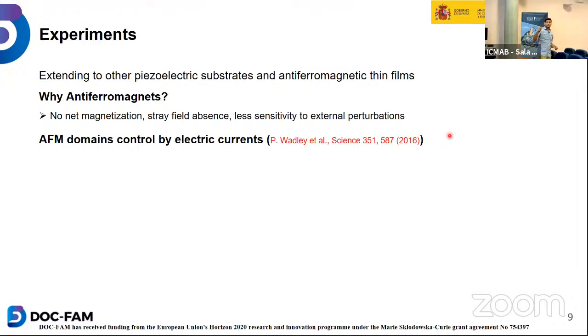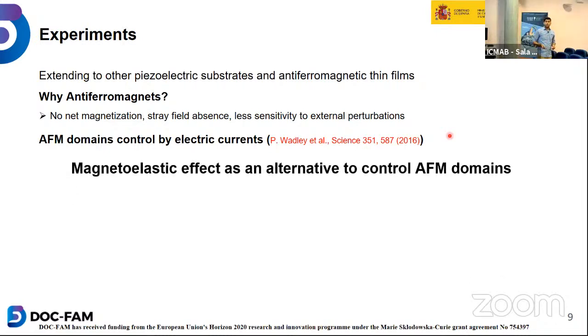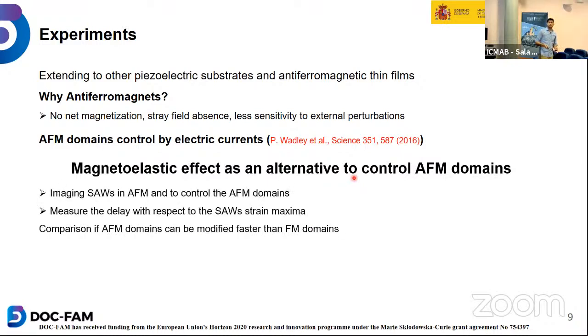Antiferromagnetic domains have already been controlled by electric currents. That has been reported. But we want to see the magnetoelastic effect as an alternative to control antiferromagnetic domains, because it is easier and less energetic. It requires less energy compared to the electric current, because electric currents can cause ohmic losses and other effects. So we tried this technique, which has already been done on ferromagnetic materials, to control antiferromagnetic domains. The purpose was imaging strain in antiferromagnets to control antiferromagnetic domains.